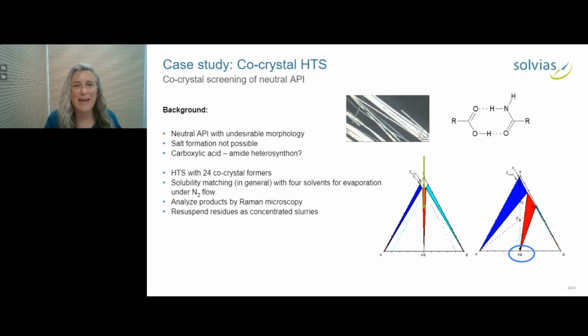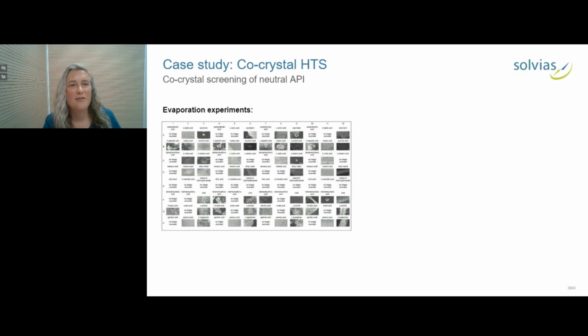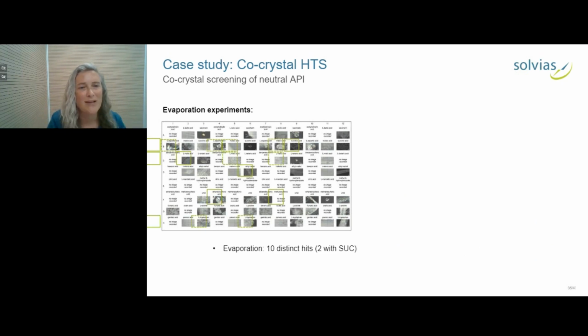And then we resuspended these residues as very concentrated slurries. And so when it's concentrated, basically you're at the bottom of the curve for solubility. So it's similar to what you would access with liquid assisted grinding. And then we can find co-crystals both from symmetric and asymmetric phase diagrams. And again, we analyzed the products by Raman microscopy. And these are the results of the evaporation experiments. These are the images. We classified the Raman spectra then.